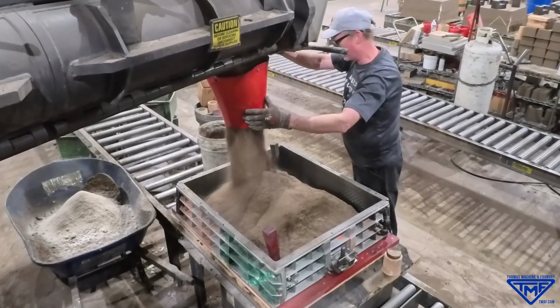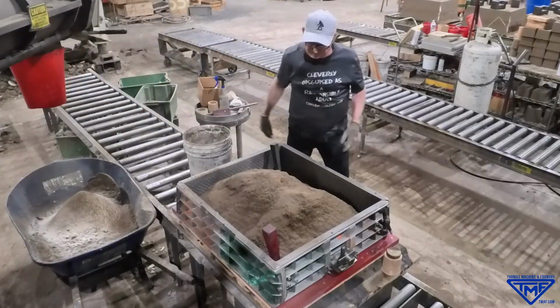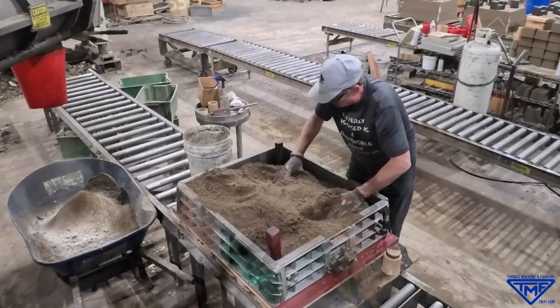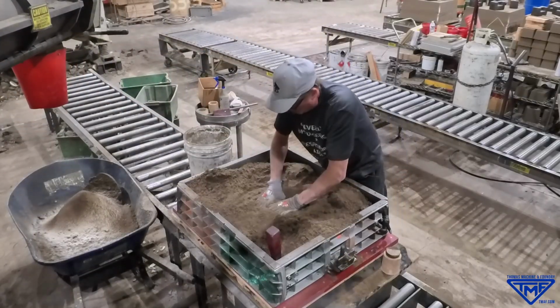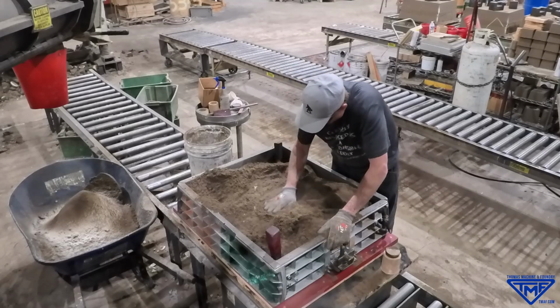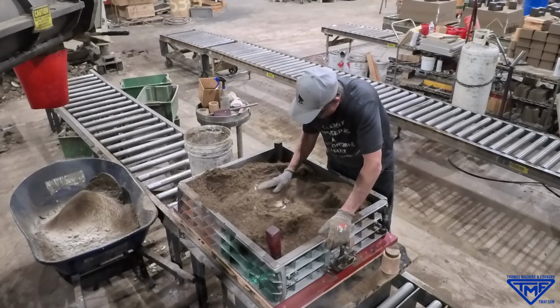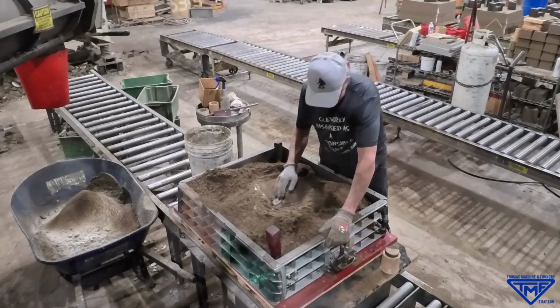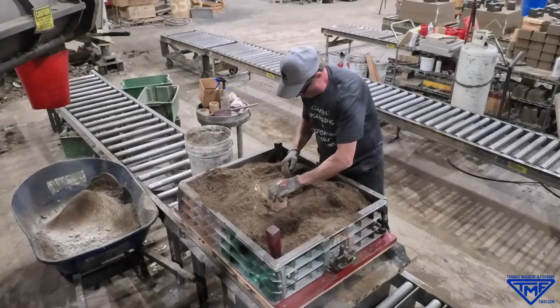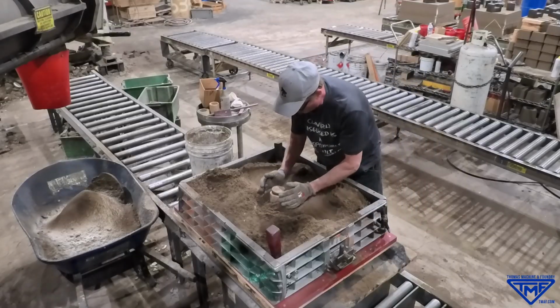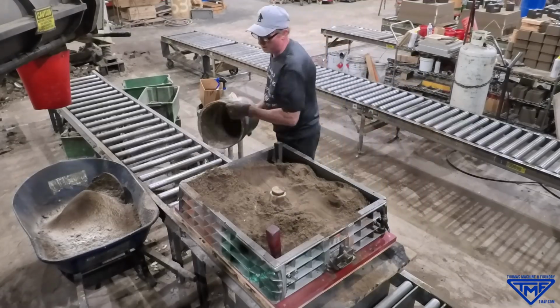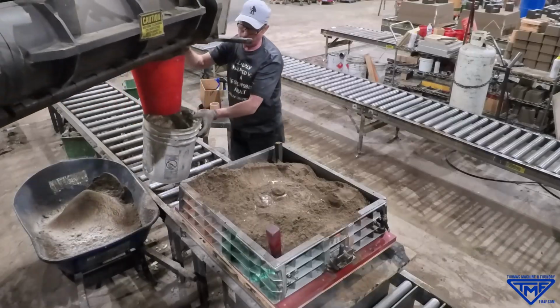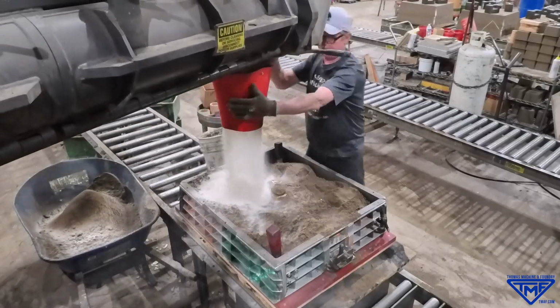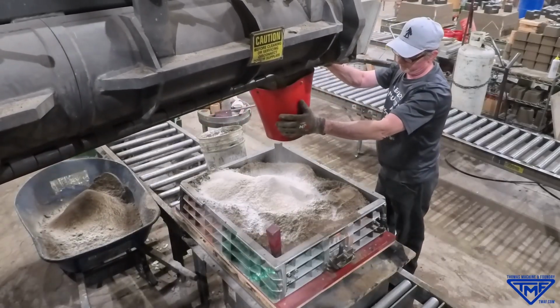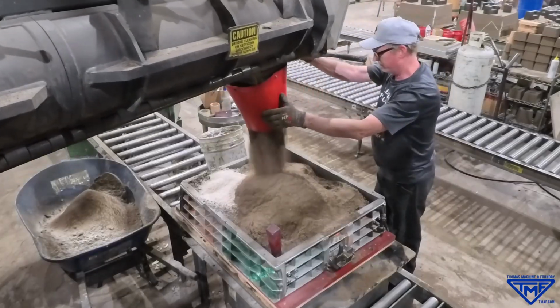Reclaim sand is simply used sand that is physically ground back down into individual grains. The darker color comes from repeated heating cycles during the casting process. Randy evenly distributes the sand around the sprues and risers and then creates a recessed area for the thermal riser. The thermal riser acts as a reservoir of molten metal during cooling. As the casting shrinks slightly while solidifying, the riser feeds additional material into the part to prevent shrink defects.